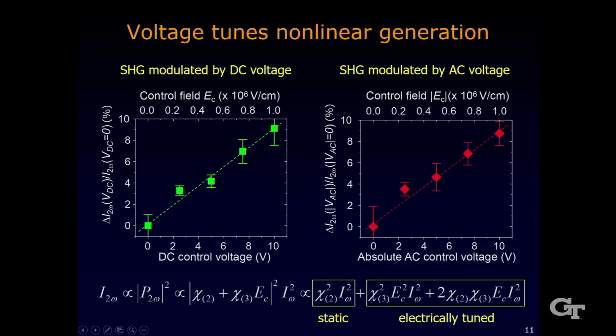From both AC and DC control, you can see that the outgoing harmonic generation is proportional to the control voltage. And this linear behavior results from, actually there's some theoretical analysis. Actually, in our system, there's both Chi3 and Chi2 induced by the surface structure. That is why the last term dominates, so you have this linear response.